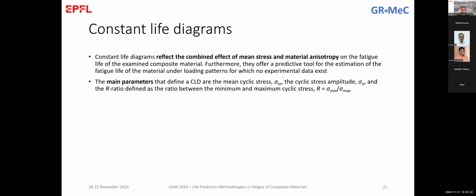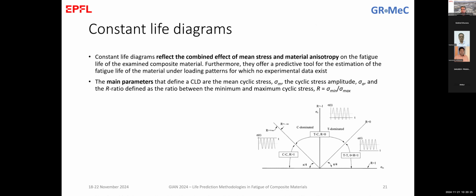So this is more or less what we have with the SN curves. And then we go to the CLDs that, again, are models that summarize the results that we have from SN curves. And these models reflect the combined effect of the mean stress and the material anisotropy. The mean stress effect is obvious, they show it by switching between the different SN curves during the diagram, and the anisotropy of the material is reflected because we see different behavior in compression and tension, and different behavior in tensile-compressive regions.